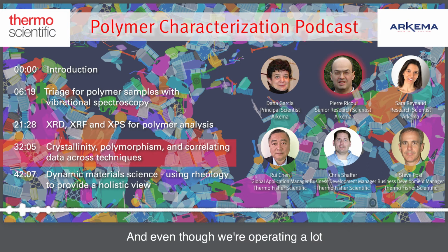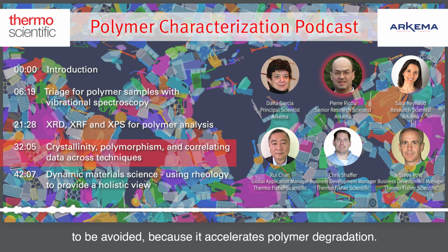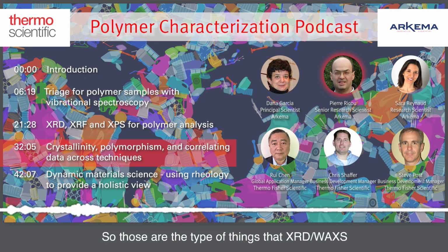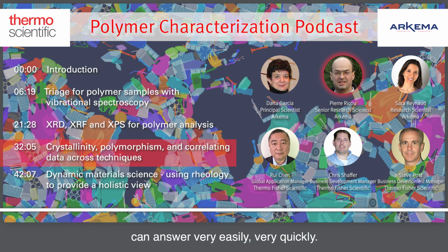And even though we're operating a lot in the polymer world, we're also looking at inorganic materials. Obviously, one of the big traditional questions in the polymer field is that titanium dioxide is used as a pigment. It makes white. It also has UV protection properties, but you want to make sure you're using the correct polymorph of the TiO2. So rutile is desired. Anatase is absolutely to be avoided because it accelerates polymer degradation. So those are the type of things that XRD WAXS can answer very easily, very quickly.